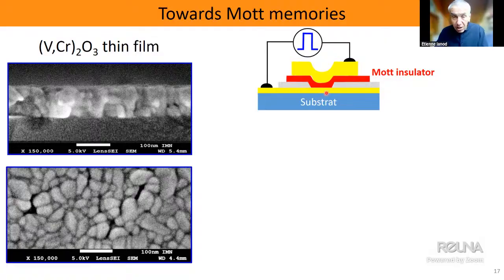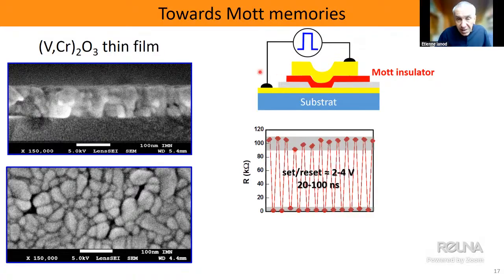And this allows us to check the property, but at a very low spatial scale. And what we have seen is that when we do that, we have been able to induce a drop of resistance by applying an electric pulse initially. But what was extremely interesting is that the application of a further electric pulse allowed the system to go back, to relax to its initial state.